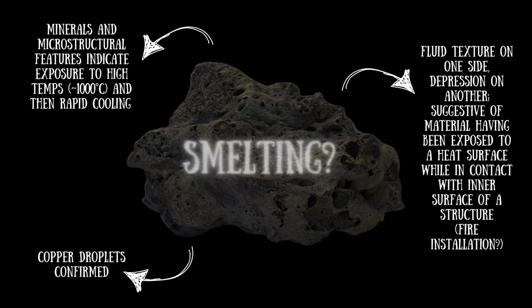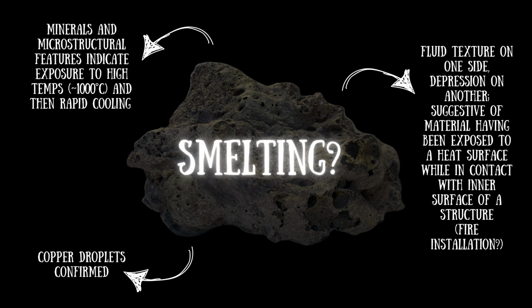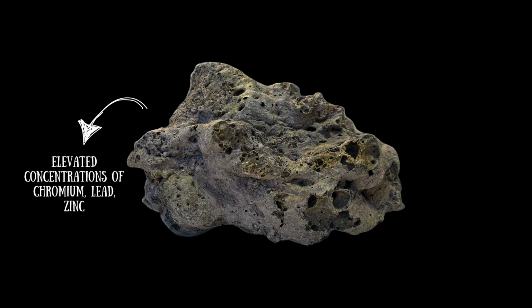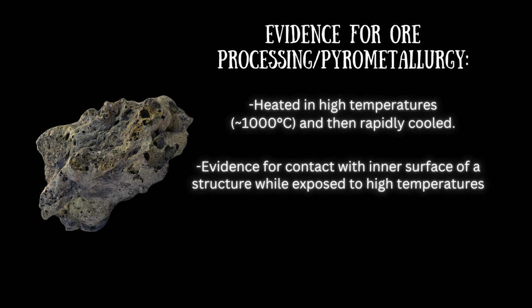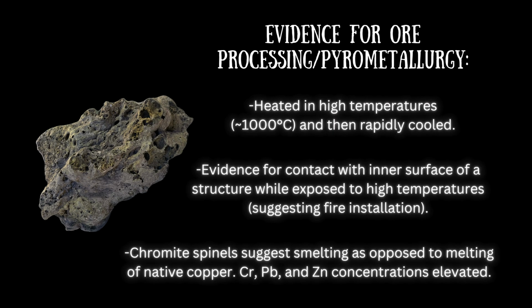But is there evidence of smelting? Although this can't be 100% confirmed at the moment, ore processing is suggested from the finding of elevated concentrations of chromium, lead, and zinc, since these are impurities associated with copper ores. It's also suggested from the finding of chromite spinels, which point to ore processing as opposed to the mere melting of native copper. Together, all of these suggest a potential association between this vitrified soil material and ore processing at Gre Filla.